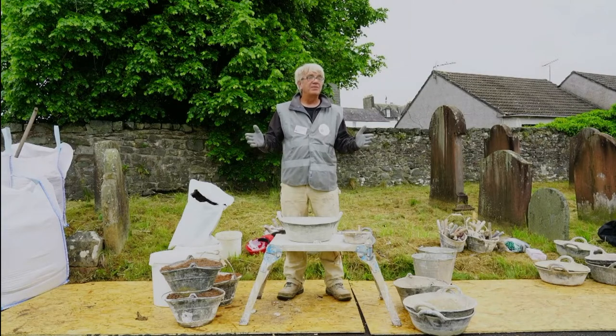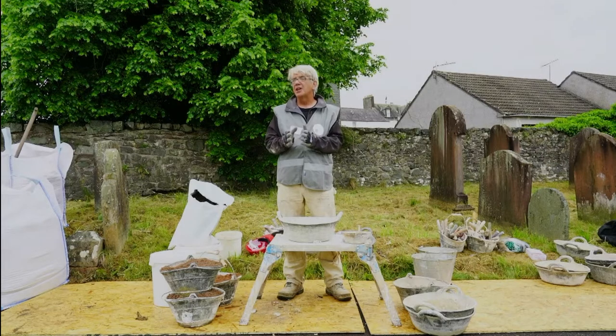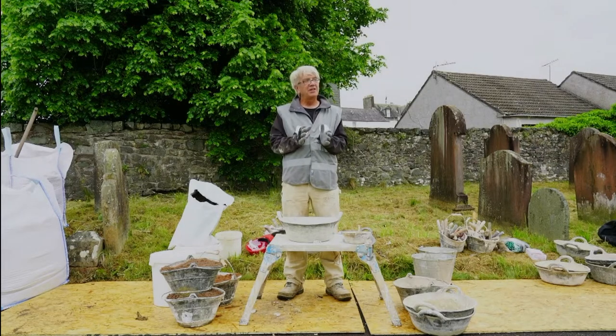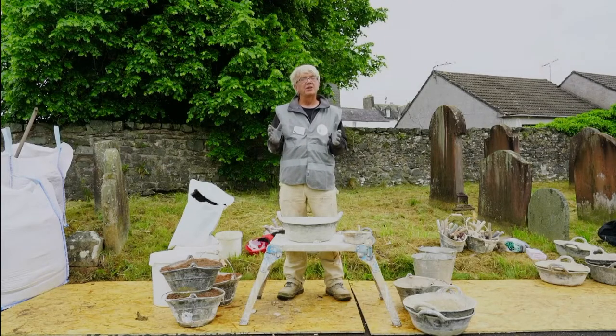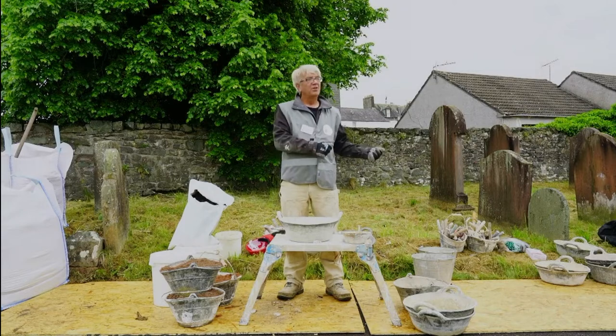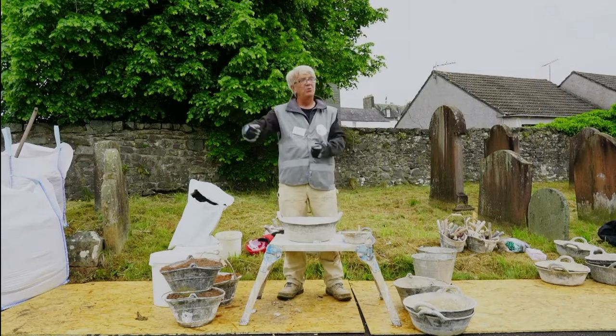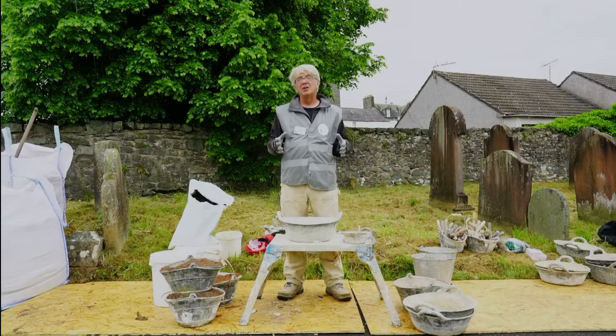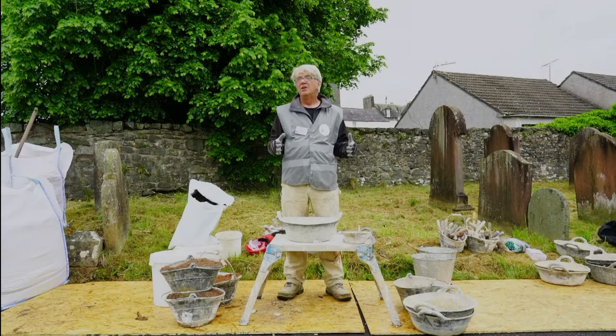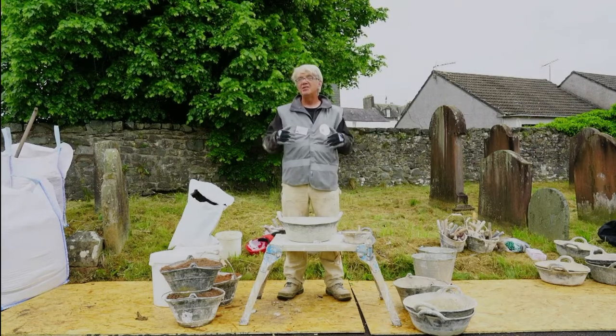And that was after 1815. We had a little dalliance with NHLs at the end of the 19th century. It's the first time that you see people suddenly talking about protecting the work, throwing buckets of water on the wall for as long as you could after you built that wall, because natural hydraulic lime demands loads of ongoing hydration, far more than anybody in this country or in the world gives it. It needs to set properly.